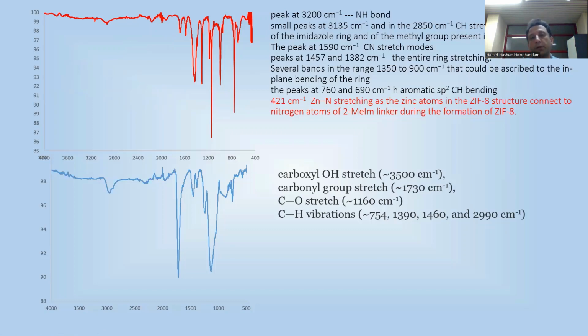In the next step, the structure of the nanocomposite must be confirmed with FTIR and SEM images. In this slide, we can see the FTIR of ZIF-8 on top and ZIF-8 coated with molecular imprinting polymer below. As we can see in the figure, we have a peak related to imidazole, the zinc imidazole complex, which confirms preparation of ZIF-8. Also, in the blue one, we can see peaks related to the polymer, peaks of CO, CH, and OH. We can see them in this spectrum.